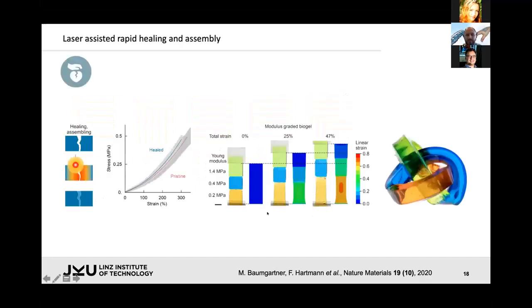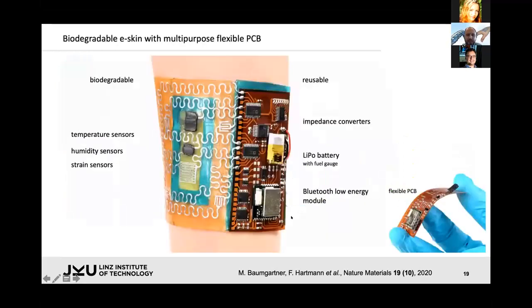Since it's a thermoplastic elastomer, you can actually use heat to manufacture structures out of it, and you can even go ahead and design modulus graded substrates by using a laser to kind of assemble these structures. So the different colors here correspond to different mechanical moduli. And if you have this assembled, you can put, for example, electronic components at areas of the patch that are less strained and the sensors at areas that are more strained, or you go ahead and make complex 3D structures that eventually are not possible with 3D printing. Or you repair your structure. If it's broken, you can just melt it basically together again, and it will continue to work.